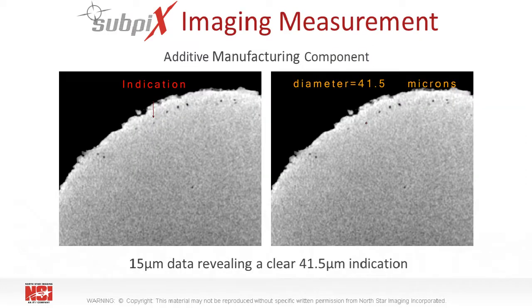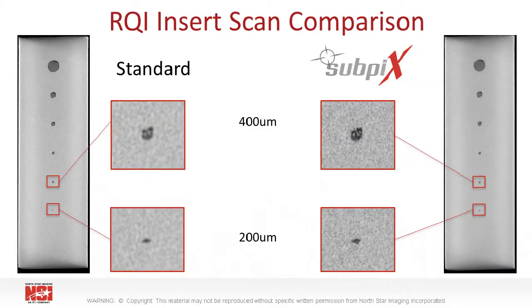The technique for this subpix scan of a printed metal part generated a 15 micron voxel size, which revealed multiple porosity toward the edge of the part, the smallest being approximately 42 microns. When we scanned one of our RQIs with the 2 different techniques, the 200 and the 400 micron powder filled indications were visible with both the standard and the subpix scan techniques. However, the subpix displayed more detail about the indication.